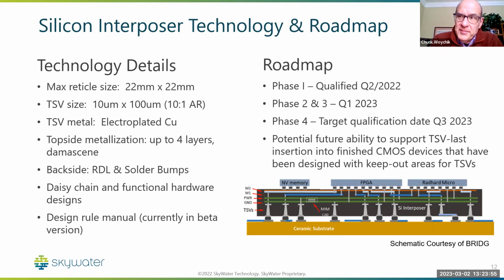In addition, what we are offering is a daisy chain and test vehicle. This is going to be a 30 millimeter by 40 millimeter silicon interposer, which is quite large, and it'll have 3 die that'll be solder bump attached on the top side. And as you can see in the back on the right-hand side, there's a schematic of the test vehicle. So there's going to be the daisy chain, which is really to get the bugs out of the process and also to do reliability testing. But it will be that larger format. This design will be built on a ceramic substrate. That's mainly due to our customer requirements. But we'll offer the reliability data, and then when the full functional module is built, the functional data for that.